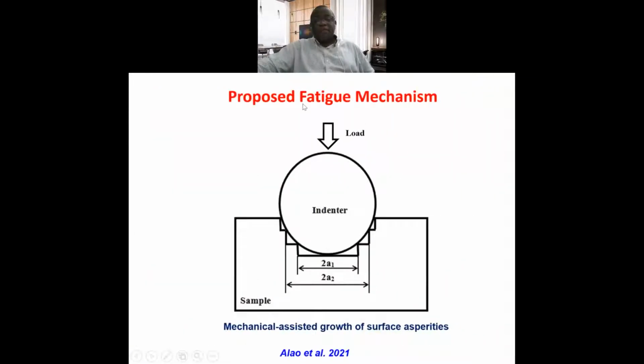So now this is the proposed fatigue mechanism. In a cyclic load, both cone crack and quasi-plastic yield will occur because of the fluctuation of the load. Then as the load is increased, the cone crack will extend due to a phenomenon called slow crack growth, while the quasi-plastic will lead to coalescence of micro cracks.